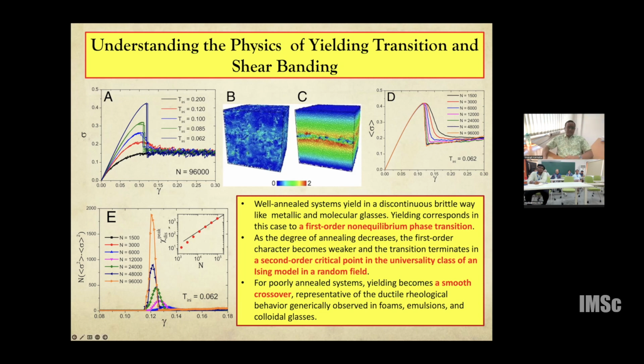But it's very, very clear that as one looks at these shear bands in increasing system sizes, the stress drop, as shown in panel A, becomes larger and larger. And if you look at the corresponding susceptibility, which tells you how much fluctuation you have around this yielding process where the shear band appears, that susceptibility turns out to grow with increasing system size. And this somehow signals that there is a large length scale coming up, and this length scale is obviously connected to the spanning shear band that one sees.